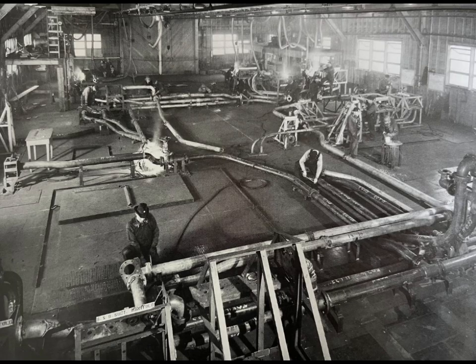It was to improve everything around welding: better steel chemistry, higher fracture toughness, improved ductility at low temperatures, design changes eliminating rectangular corners in favor of rounded openings. Crack arresters, belts of different steel composition placed strategically to stop crack propagation. Better welding rod composition, improved technique training, more rigorous inspection. The question wasn't whether welding was inherently inferior to riveting. Properly executed welds were stronger than riveted joints.